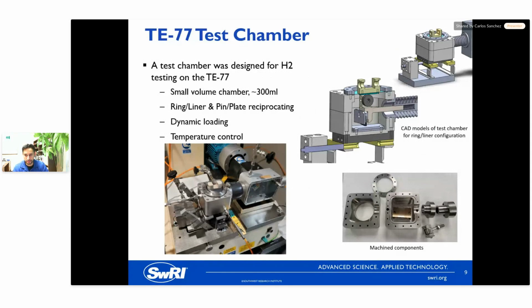Like I mentioned before, the TE-77 is a two-part design where you have the cam box on the right side. It transmits the linear motion into the test cell. There are several sections that have linear seals, and it's all well encapsulated there. Other than that, it's able to run just like a typical TE-77. So you have dynamic loading, temperature control, external friction measurement, and so forth. And we're able to run a ring and liner test in here pretty effectively.